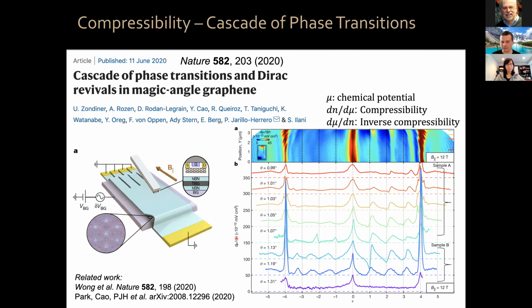And in particular, it can measure this dμ/dn, this inverse compressibility that you can think of in single particle physics as the inverse density of states. So for example, gaps appear as high peaks because in a gap you don't have density of states, so you have a peak in the inverse compressibility, okay?